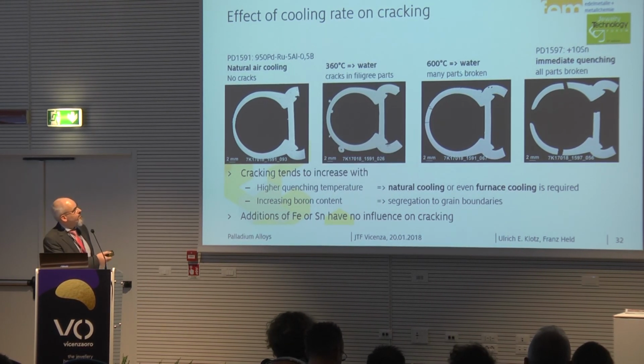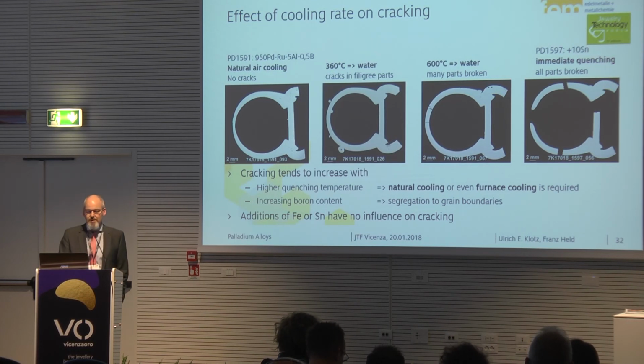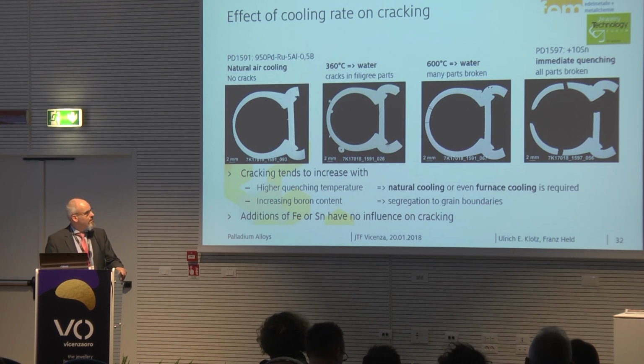And even if you quench from 600 degrees, still many parts are broken. If you quench from a lower temperature, there are still the filigree parts that are broken. So this means you have to cool these flasks down to room temperature very slowly. Specifically if you add boron, this is an important point.